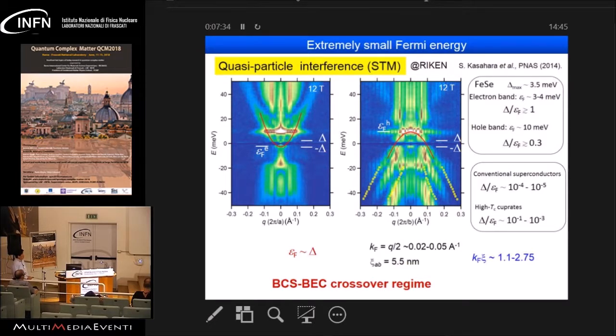For the electron band, we get delta over EF of the order of unity. It's almost more than unity, which is very large. And for the hole band, we get delta over EF of about 0.3. So these numbers are quite large, much larger than in other superconductors. We can also get the information of kF and xi from the upper critical field measurements, and we get a value of xi kF which is of the order of unity.